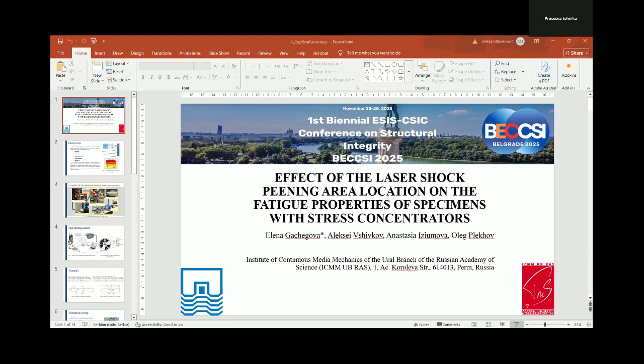After treatment, we measure residual stresses using the automated system MTS 3000 Restan. And a little bit more about this system. We measure residual stresses using the hole drilling strain gauge method in accordance with the international standard ASTM E837.